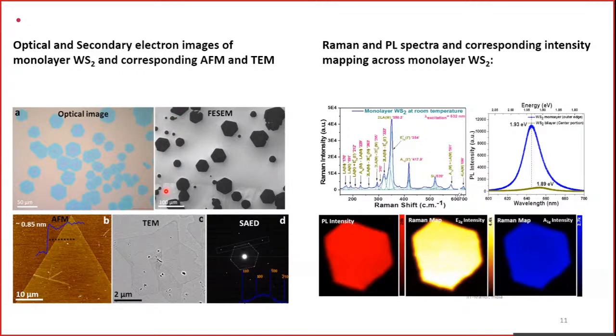Just to avoid confusion about the quality of the material, I'll only show one slide of quick characterization. After the growth, we need to ensure it is a monolayer. So we look at it in the optical microscope and FESEM just to get an idea about the lateral dimension. Then do AFM to confirm the monolayer. Typically, it's around 0.8 nanometers for the WS2. Then we also rely, more importantly, on Raman spectroscopy as well as photoluminescence spectroscopy.